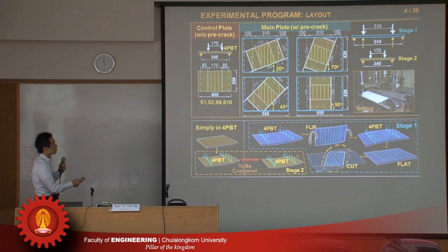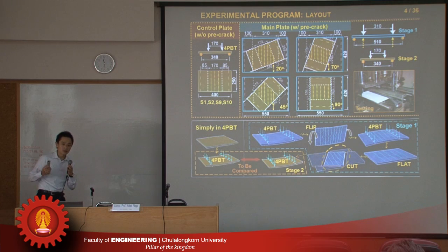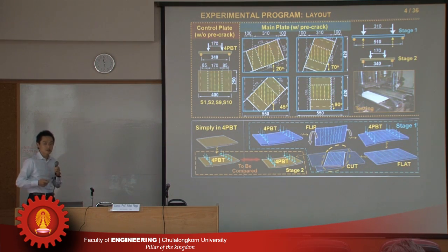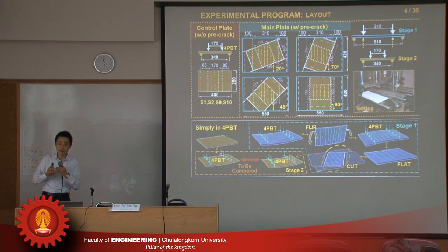So we have selected 4 types of degrees of the inclination of the initial damage. So firstly we give the initial crack, and then we apply the load. So that situation represents the tensile test with some damage with a certain angle, like 20 degrees, 70 degrees, 45 degrees, 90 degrees, and so on. Then we can check how the initial cracking slides after the cracking.